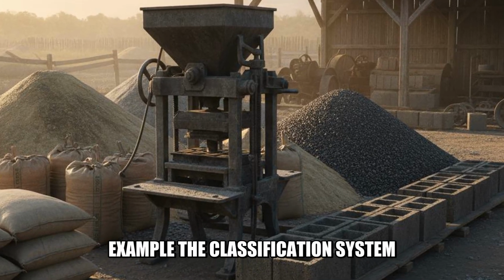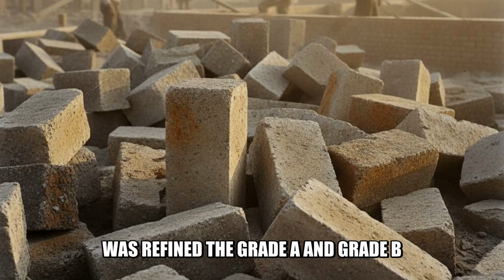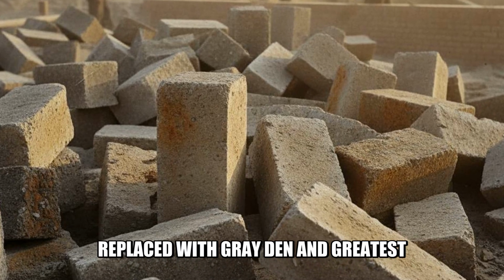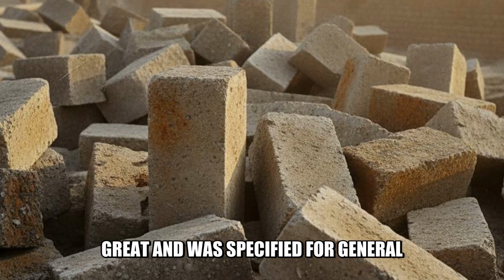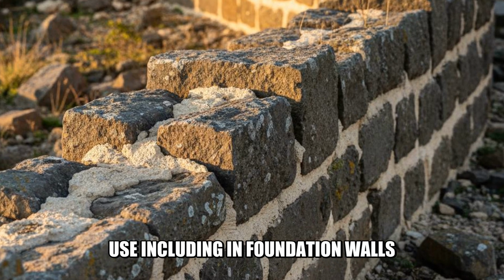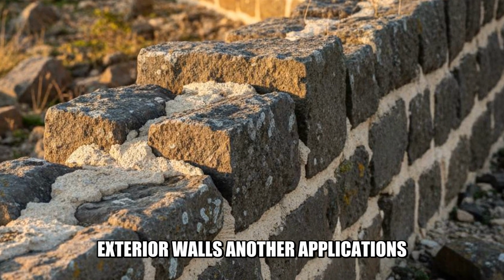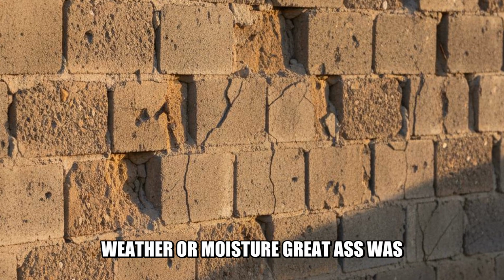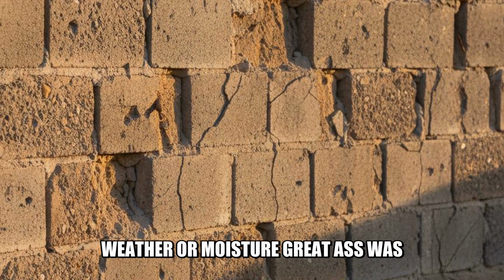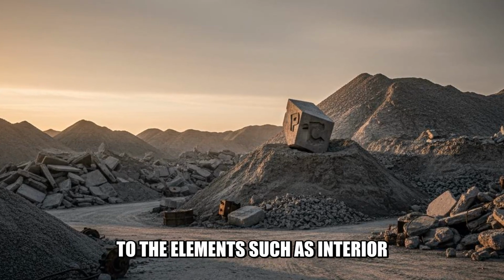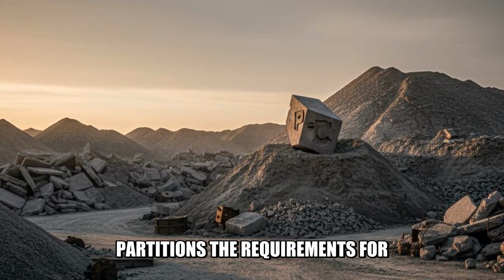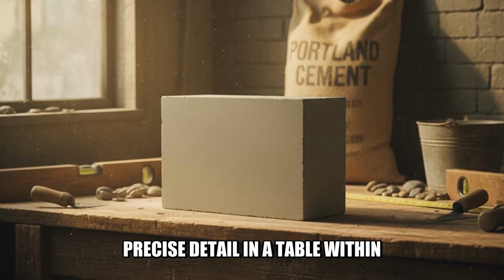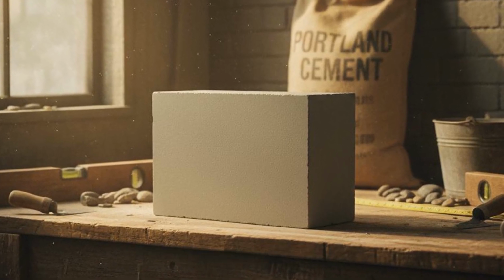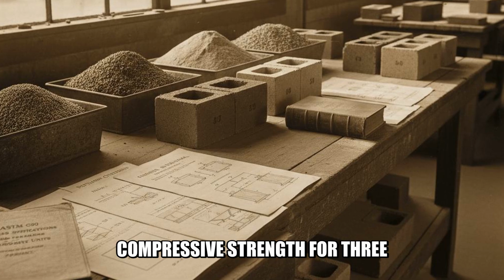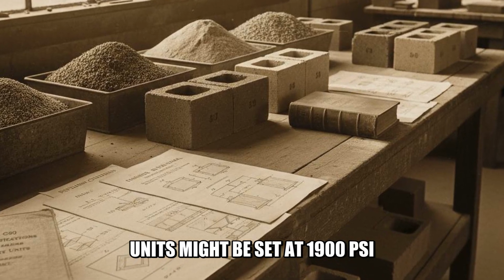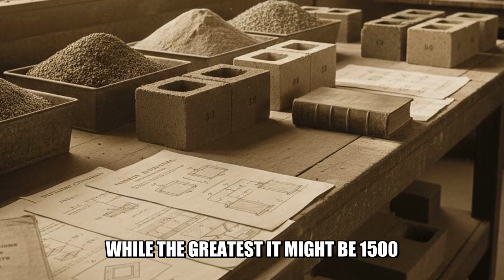For example, the classification system was refined. The Grade A and Grade B designations were eventually replaced with Grade N and Grade S. Grade N was specified for general use, including in foundation walls, exterior walls, and other applications where the block might be exposed to weather or moisture. Grade S was limited to use in walls not exposed to the elements, such as interior partitions. The requirements for each grade were spelled out in precise detail in a table within the standard. For Grade N, the minimum average compressive strength for 3 units might be set at 1900 psi, while for Grade S it might be 1500 psi.